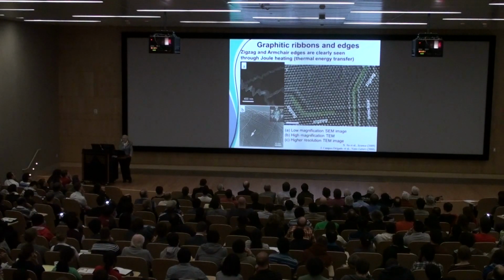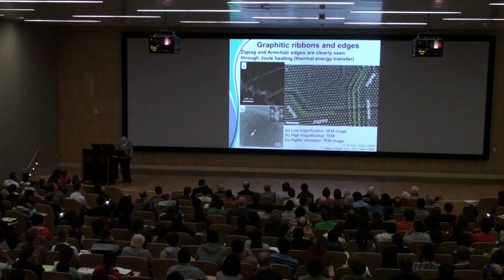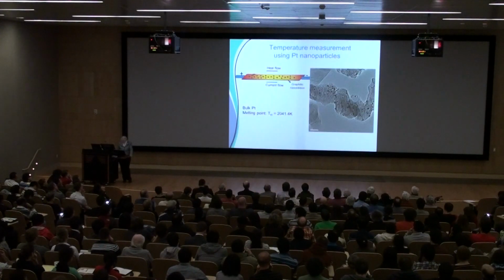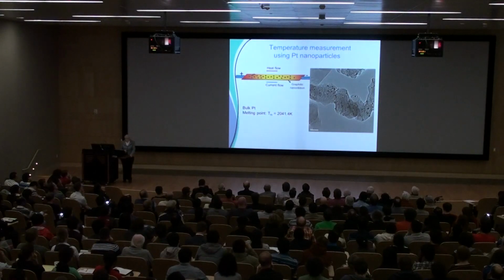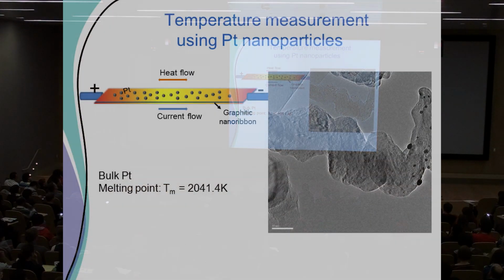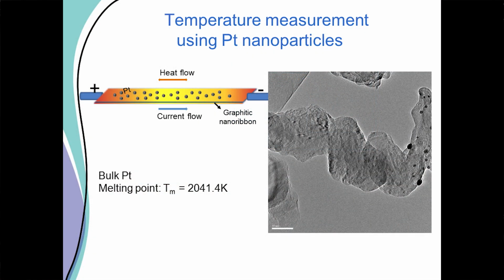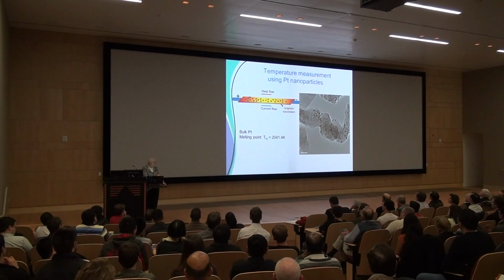You can pick out just from visualization the armchair and zigzag edges. So this is a recent paper, in Science magazine or something like that. And then people ask us, well, what temperature are you at? Well, we had no idea, so we put in little platinum particles. They melted at about 2,000 Kelvin, and we could watch them melt. So that gives you an idea, not very accurate, but an idea of what the temperature is.